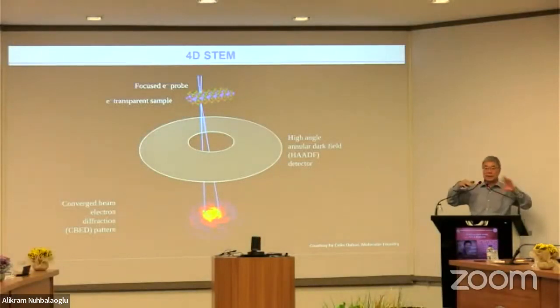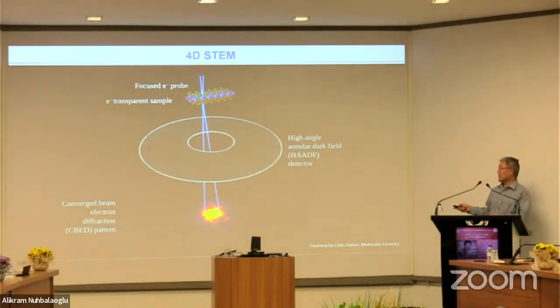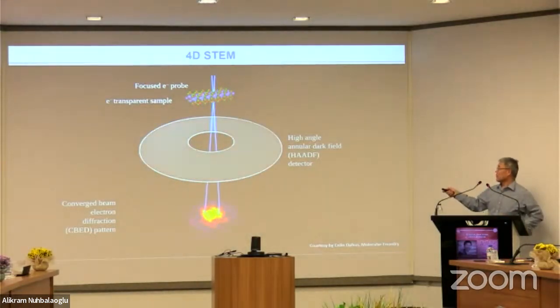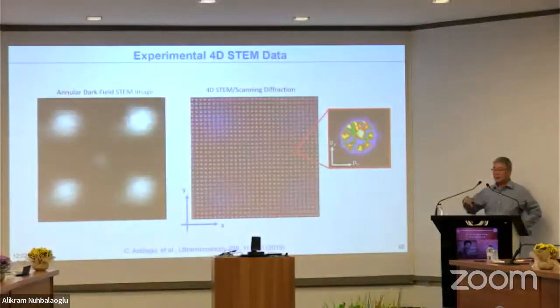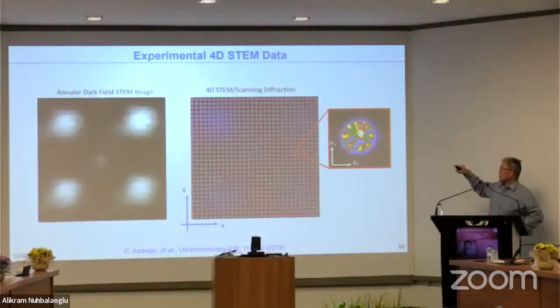So this tells you how 4D STEM can be done. This is a movie done by Colin, simply showing you how 4D STEM works. The electron beam will scan through the specimen, and at each scan point you get a diffraction pattern. This is a converging diffraction pattern. You collect this data. This is 4D data, right? Then you analyze this data, and you will be able to get the momentum changes and then the electric field. So the method is, we now think, quite confident to work.